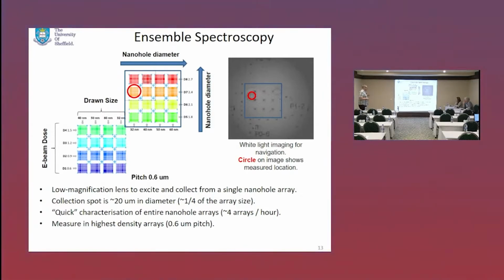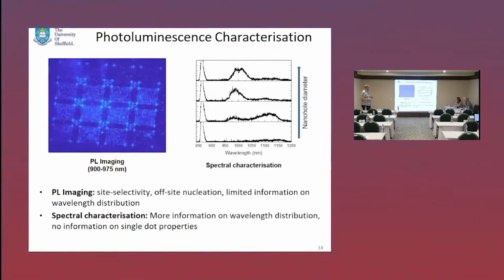A quick method of doing this would be to basically sample the entire array. If we do luminescence on the entire array, we're going to get no indication of site occupancy and so on, but we will get an indication of the homogeneity of the line widths and so on, and we can move from site to site relatively quickly. The next thing we could do, which is also quick, is imaging. It requires a very expensive camera that has to go back to have its shutter replaced every once in a while.